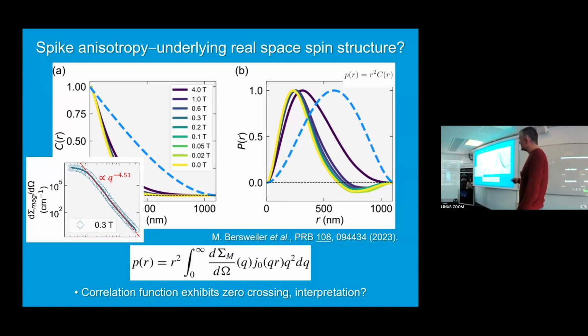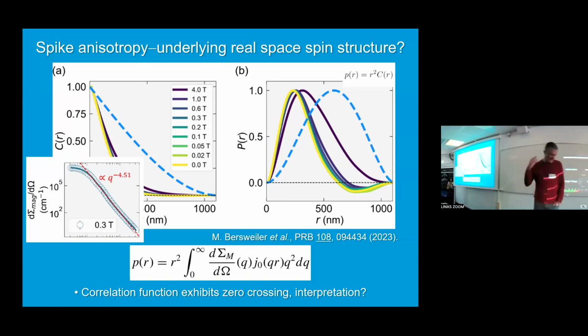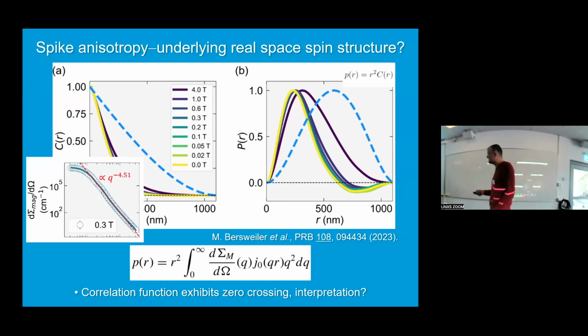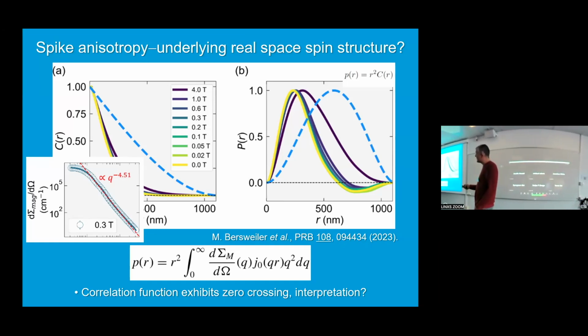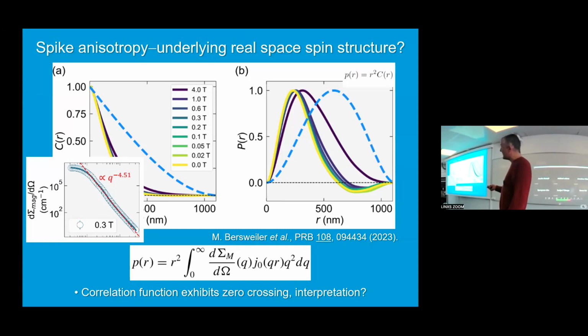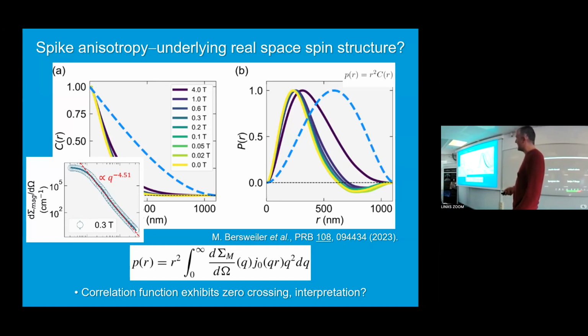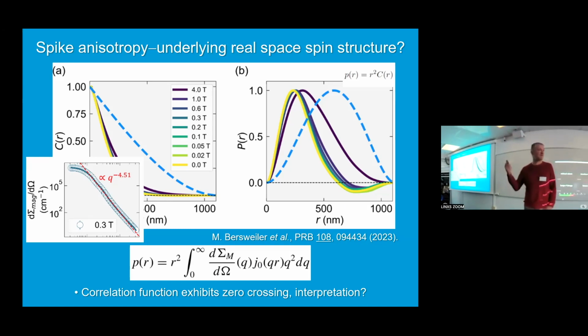And also here you see this exponent, which deviates from what you may know as the Porod law, which, I would say, in magnetism you find relatively often. In particular, for inhomogeneously magnetized materials, it's quite common to find exponents here that are larger than this exponent of 4.